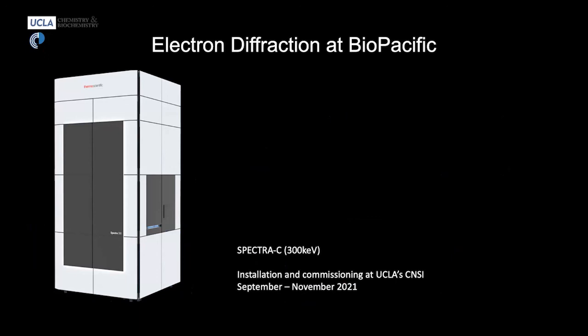What limits the periodicity you can detect in your diffraction patterns? Is it Debye-Waller effects, electron dose, or something else? That's a great question. The signal that we're seeing is coming from a periodic structure. And so if your structure is not periodic at all, let's say you have a purely amorphous structure, like a glass or something like this, we would not be seeing the type of diffraction that we see here. We would not see these key locations of constructive interference that would allow us to then determine a structure for that assembly.